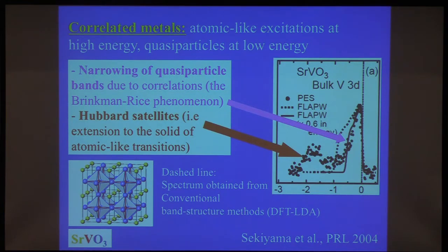And this effect is underestimated by traditional state-of-the-art electronic structure calculation. The dotted line is DFT LDA, calculated exactly in the LDA approximation. So you are lacking a correct description of the quasi-particles, and you are lacking the high energy atomic-like excitations. So how can you repair this problem?